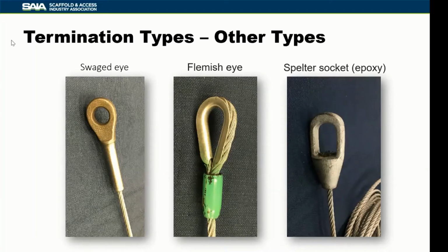I think if you look at most literature, it will tell you that for the size wire rope that we were looking at, which is the 5/16 or 8 millimeter, most of the compression sleeve manufacturers only specify that you need a single compression sleeve. So the fact that you may use 2, I don't know that there is a hard and fast rule that says exactly how far those should be spaced apart. So as I said, we use the rule of thumb of one rope diameter, and that's what was used in the preparation of the samples for these tests that were conducted.